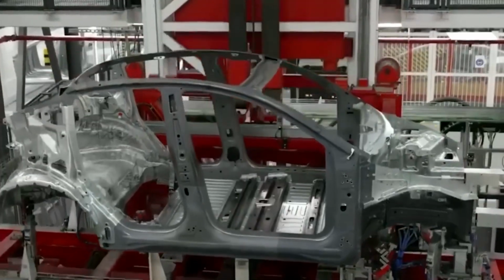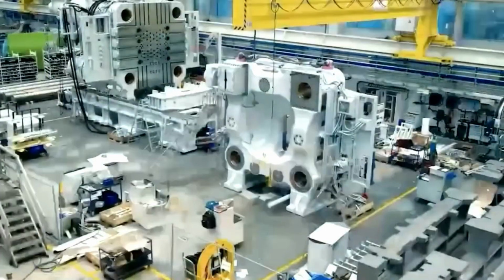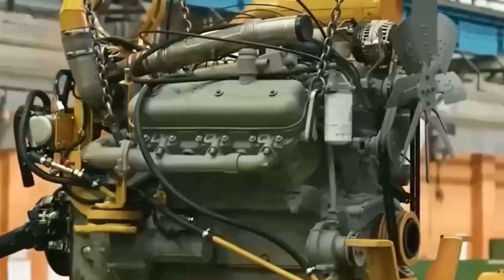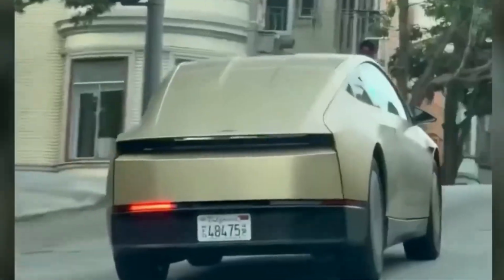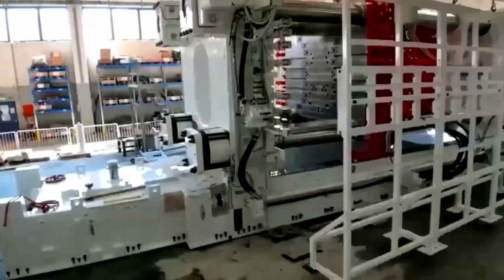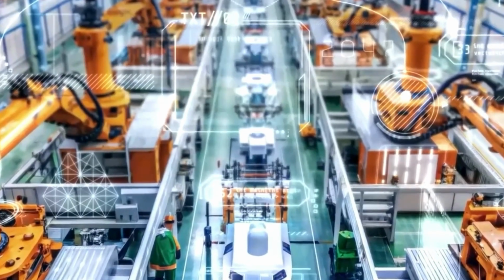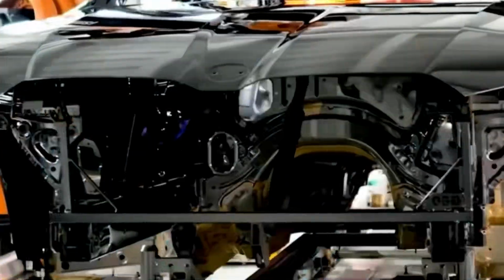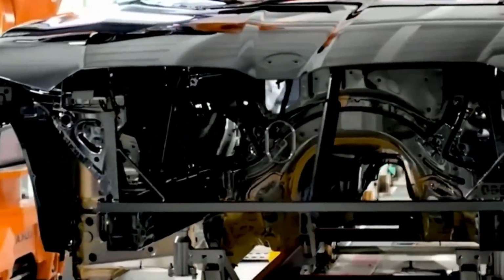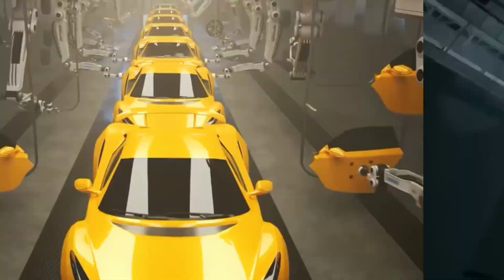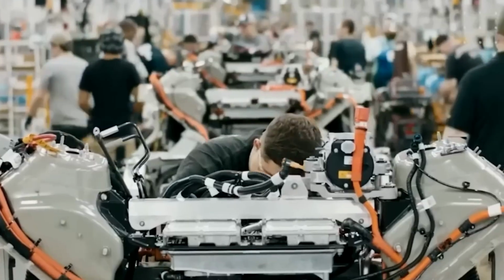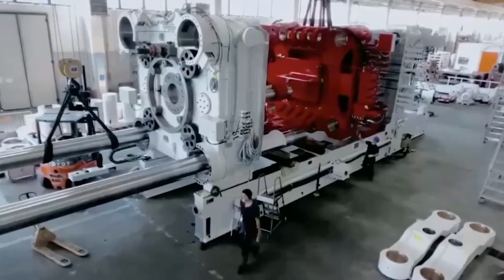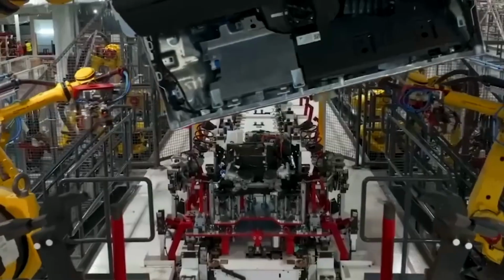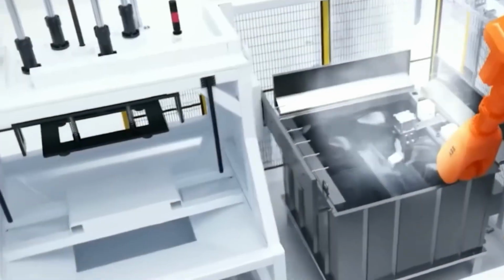Once the mold is filled, cooling begins, and that's where all the technological significance lies. Inject the metal too fast and air bubbles form inside, weakening the part. Too slow and the aluminum starts to solidify before it fully fills the mold, and the casting is scrapped. That's why the cooling system is designed to maintain a uniform temperature throughout the entire process. Once the casting is complete, robotic systems extract the part, trim the excess metal, and send the component to quality control.